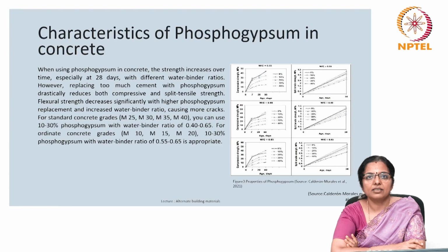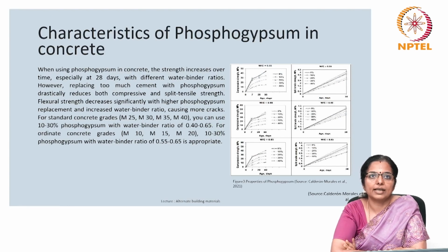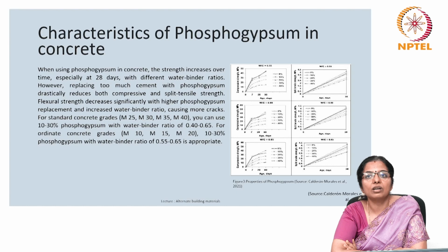Let us look at the characteristics of phosphogypsum in concrete. Using phosphogypsum in concrete has interesting effects on strength. As the concrete ages, its strength increases, especially after 28 days, with different water binder ratios. However, if we replace too much cement with phosphogypsum, the strength drops a lot, causing issues. The flexibility of the concrete, known as flexural strength, also decreases when we use more phosphogypsum or increase the water binder ratio, leading to more cracks.